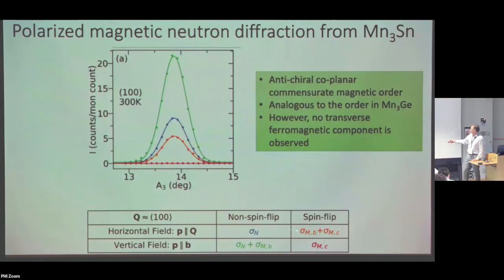On the other hand, when I take spin flip, again with neutrons polarized along wave vector transfer, then I get all of the spin polarization, which is normal to wave vector transfer, and that's the orange peak. So this has broken down the nuclear contribution and the magnetic contribution, and that's a really wonderful thing, because I can know for sure how much is magnetic, how much is nuclear. If I do unpolarized, I'm just going to see the sum of those two. Actually, sorry, I can see the sum when I go to this channel here. So it's a non-spin flip channel with vertical field, and then you can see that summing these two to each other, I'll get up to this number.